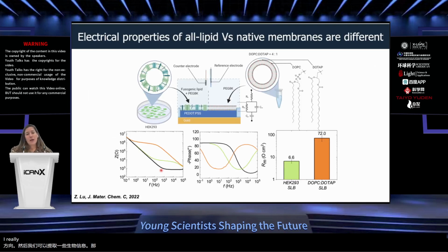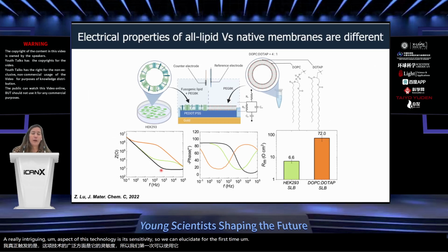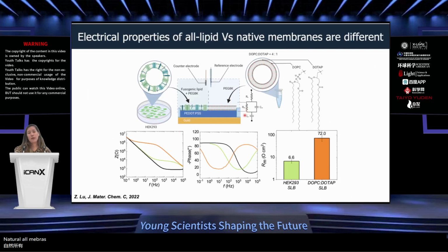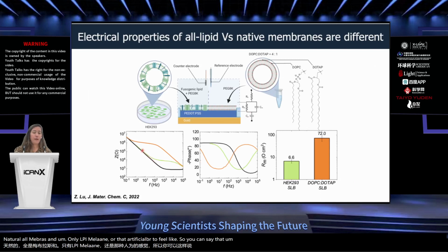A really intriguing aspect of this technology is its sensitivity. We can elucidate for the first time, in the sense that it's not possible with optical methods such as FRAP, differences between natural membranes and only-lipid, or artificial, membranes. You can see that the change in the shape of the impedance plot for a natural membrane is completely different from that of the tightly packed artificial membrane.